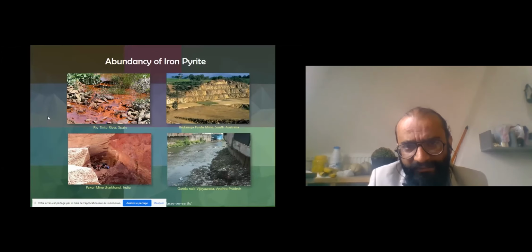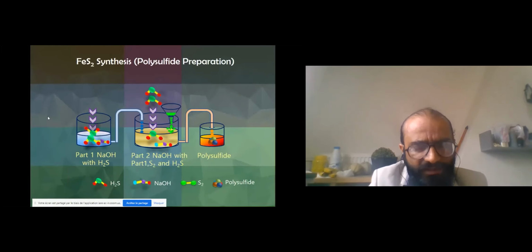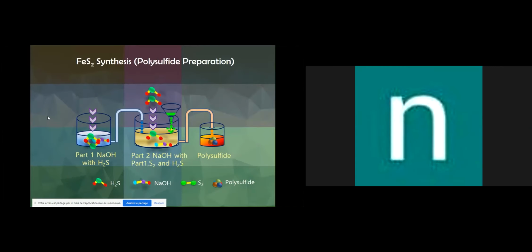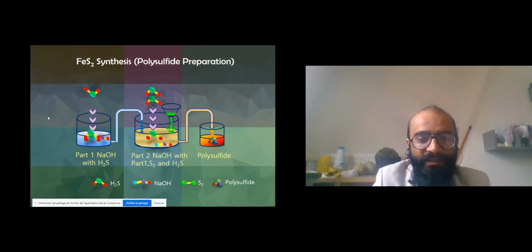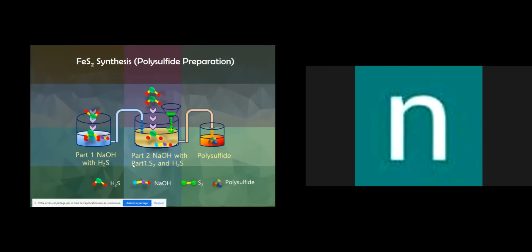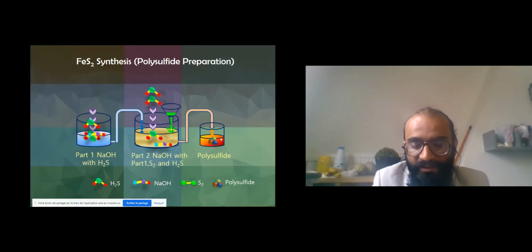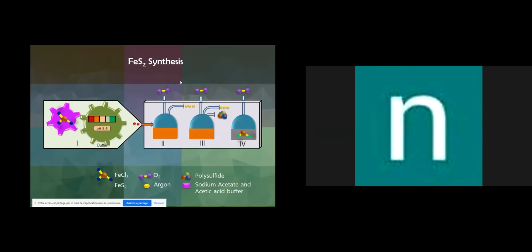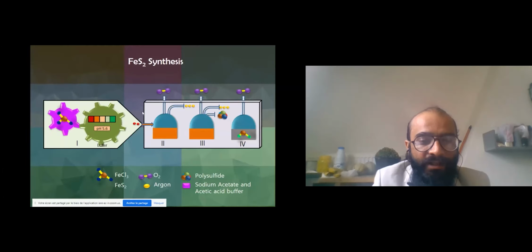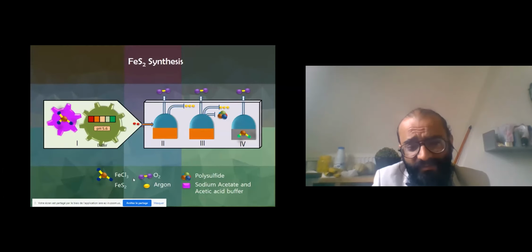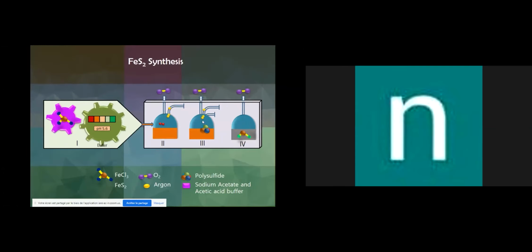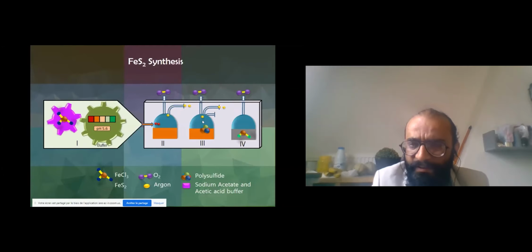If it is extractable, we can use it, and we have to work on this. But is it possible to synthesize it easily? It is. Let me show you very quickly. A lot of people have done this work also, but let me show you how easy it is. We can perform it at 100 degrees centigrade. There are two steps: mixing sodium hydroxide, which has H2S, with sulfur, so you can make polysulfide in the H2S environment. Then you utilize this polysulfide in the presence of a buffer, sodium acetate and acetic acid, with FeCl3 in an inert atmosphere. You get a very efficient iron sulfide, and the temperature was just 100 degrees centigrade. That's one example.